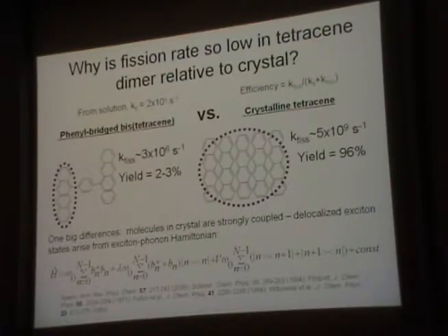And say, we know this was first observed in tetracene, and if you take the kinetics that people did with the crystal seriously, we're way off of what they had in the crystal. In the crystal, the fission rates are roughly 5 times 10 to the 9. Here we're 3 times 10 to the 6. 1,000 times faster in the crystal. That's bigger than any energy level change is going to get you. And in principle, if you believe those numbers, the yield's 96%, or if you want to look at triplet yield, it's up around 195%. If you take those kinetics seriously.